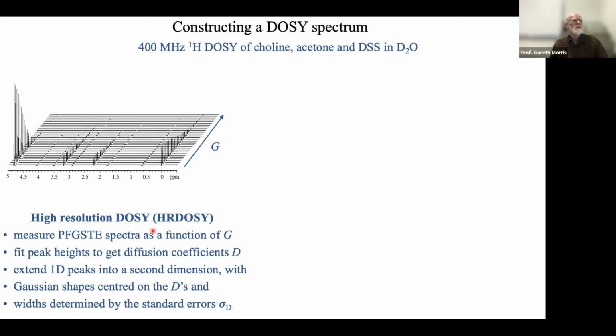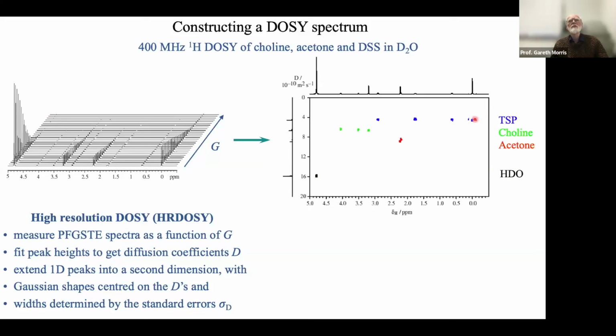What we do is to measure some diffusion weighted spectra, maybe PFG, STE, maybe one shot, whatever, measure them as a function of gradient. We're then going to fit the signal decays to theory, to the Stejskal-Tanner equation, in order to extract a diffusion coefficient for each peak. And then we extend the peaks into a second dimension and we plot our peaks in 2D form to say, oh, yeah, TSP diffuses slowly, HDO diffuses very rapidly, choline and acetone in between. But those of us who are small molecule chemists can immediately look at that and say, yeah, I have one of those. That's really useful. This is a way of looking at a proton spectrum and seeing roughly how big different components of a mixture are.